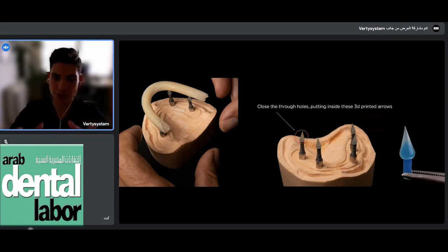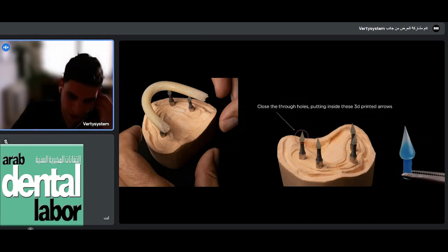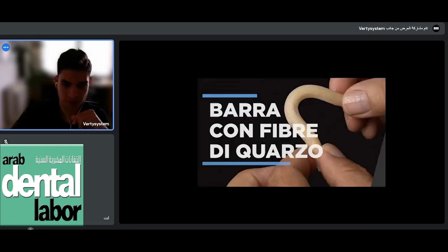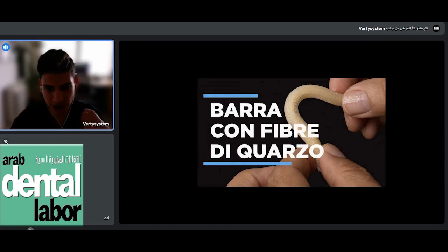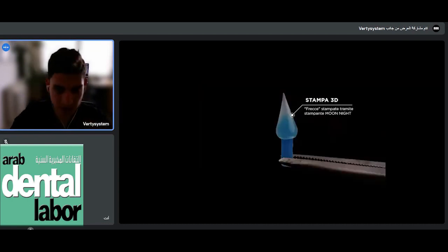It's important to do this whilst it's not hardened, because you can burn the quartz fiber bar after it hardened, because you can interrupt the fibers. Yeah, that's a little bit of the process that we do for the quartz fiber bar.